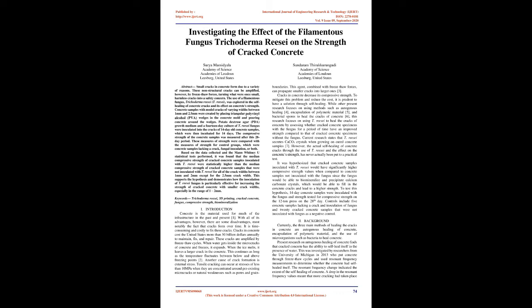A Mann-Whitney U statistical test was completed for each of the different crack widths, comparing the compressive strengths of samples inoculated with fungus and those not inoculated with fungus, and the results of the test are presented in Table 2. For 3 of the 4 Mann-Whitney U statistical tests run, for the crack widths of 1 mm, 1.5 mm, and 2 mm, the p-values received were 0.016, 0.008, and 0.032.